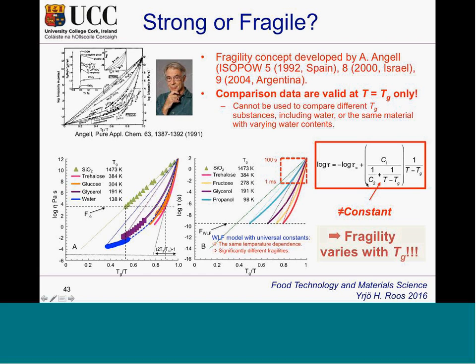Showing that Tammann-Vogel-Fulcher and WLF are actually comparable. But if the equation is more of an Arrhenius type relationship, we could get here trehalose, glucose, glycerol, water, with different fragilities. But for materials that would have the same Tg, these have different Tg. If we look at this equation, obviously they have the same point at Tg divided by T, because it's always one. But if we have different glass transition Tg values, they are in a different position on the scale and would automatically have a different fragility. So it doesn't really make much sense to me to look at this.